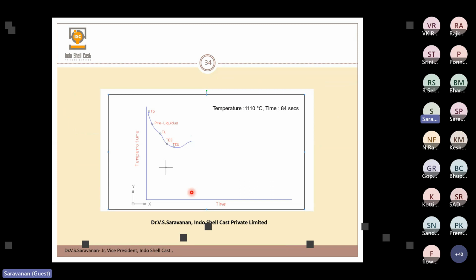So like that. Here, after TEU, as I said earlier, all the graphite actually precipitated here. During graphite precipitation, latent heat is liberated, which releases a large amount of heat. Inside the metal, millions of nuclei, or millions of graphites, actually precipitate. So the overall metal temperature will go up slightly, which is why the curve goes a little bit up. How much it goes up is very important.